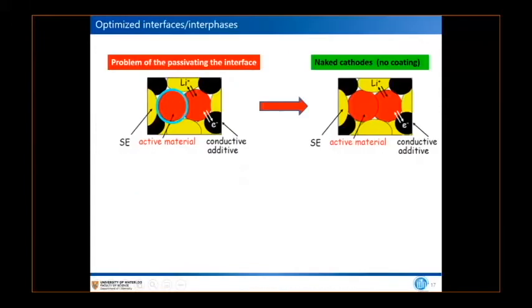And then, as I mentioned, there's this reactivity of the electrolyte with the electrode material, and indeed the material I just showed you has that. So one has to, in principle, passivate that surface. And this causes issues for manufacturing.